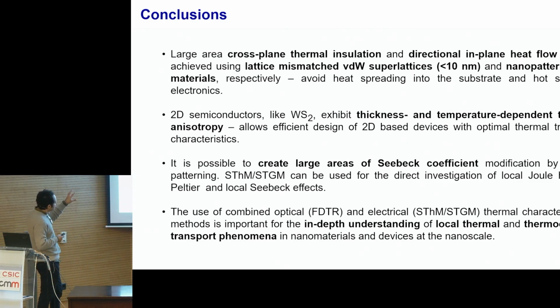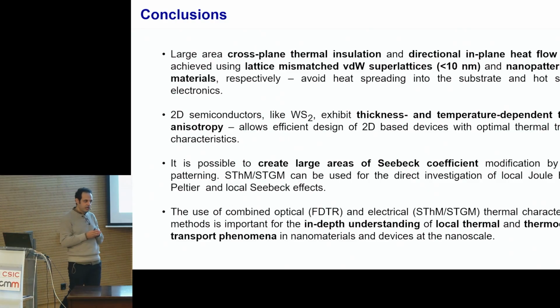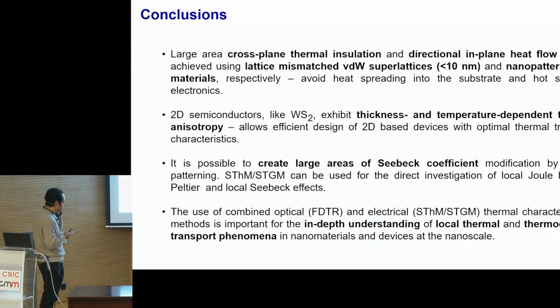We saw that the tungsten disulfide exhibits thickness and temperature-dependent thermal anisotropy. I presented a new technique with which we can really probe the thermal anisotropy in these materials. We saw that it's possible to create large areas of Seebeck coefficient modification by simple patterning, with this scanning thermal gate microscopy technique that we can really probe thermoelectric transport. And as a general conclusion, the use of combined optical and electrical thermal characterization methods is important to understand nanoscale thermal and thermoelectric transport phenomena.